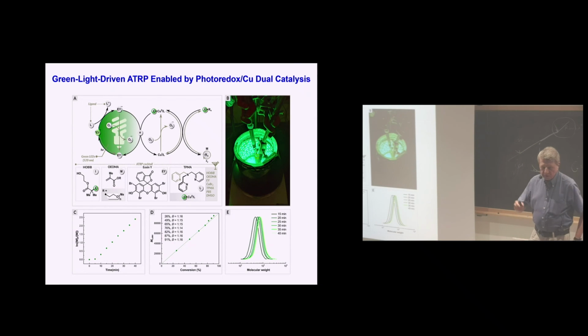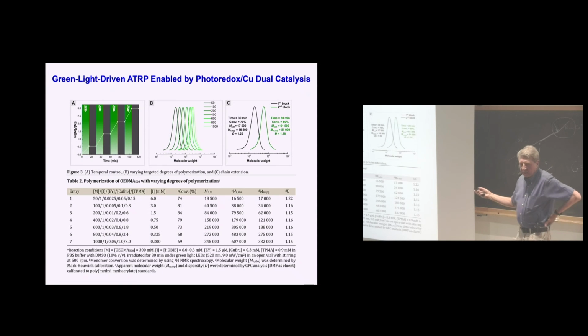So for these species, one example here is eosin Y, this dye, which can be photoexcited, and then it can react with copper-2 to reduce it to copper-1, and then you have this ATRP equilibrium. Moreover, it also has excellent oxygen scavenging possibility, the same as copper-1 will be oxidized to copper-2. So you have these reactions of high molecular weight, low dispersity, and good control. Same with the temporal control. So you have on, off, on, off, on, off, on, off. And of course, with the light, you can also have a mask, and you can make various patterns without any evacuation.